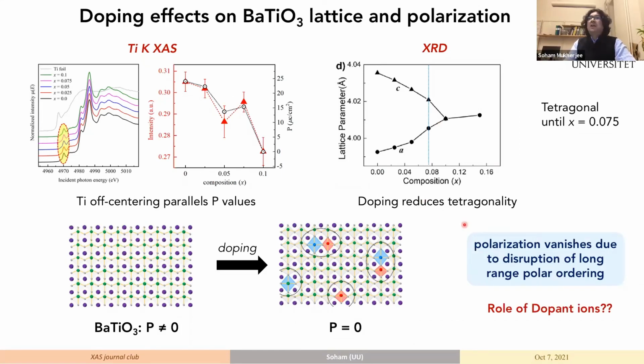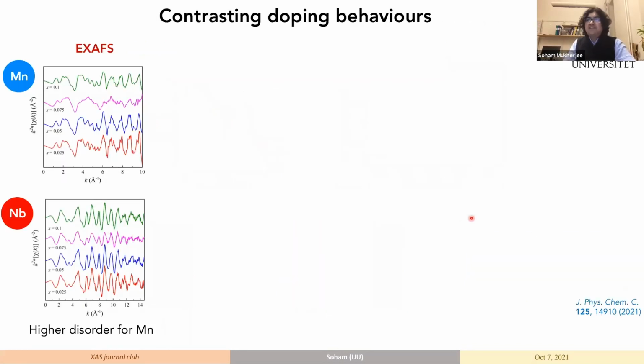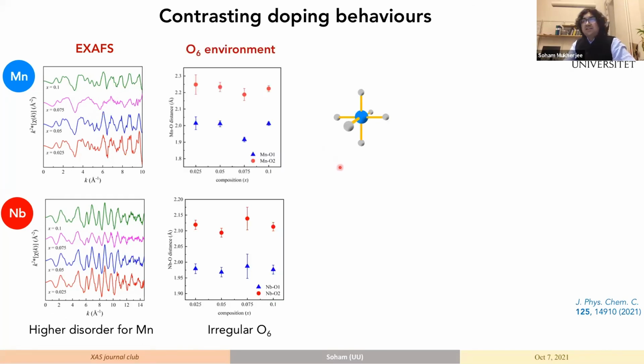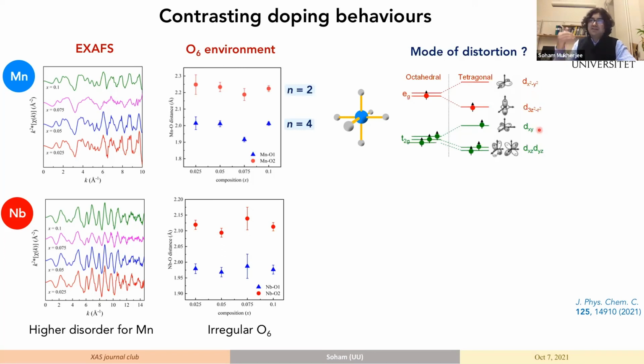So we went ahead and then probed manganese and niobium individually. And these are the EXAFS data for manganese and niobium. You can clearly see that the manganese has a bit higher disorder compared to niobium. I'll not go to the details of the analysis, but I'll just give you the results. We immediately saw that there is a classic difference between manganese and niobium. Manganese 3+, it's a Jahn-Teller active system. And we saw there's a clear 4+2 distribution of manganese-oxygen distances. And this immediately tells us why manganese leads to the change of band gap, and basically defines the band gap because of this strong Jahn-Teller distortion.